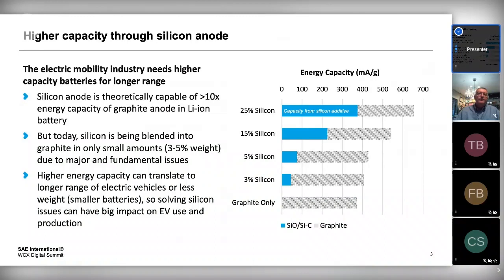When you look at the electrodes of a lithium-ion battery, on the cathode side you have a whole bunch of different materials. The anode of a current lithium-ion battery is predominantly, almost 100%, graphite. It can be synthetic or natural graphite. It's usually a blend of the two. And what's interesting about that is that when you charge your battery up and you're pushing electrons into your anode, you're causing it to swell. It swells by about 10%.